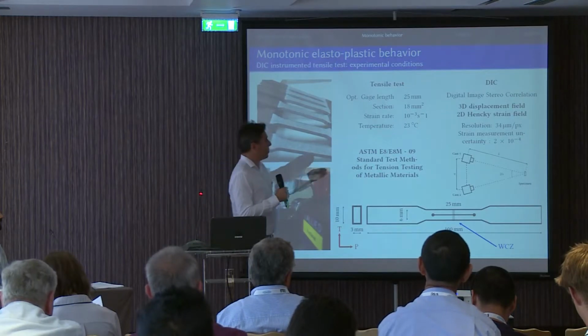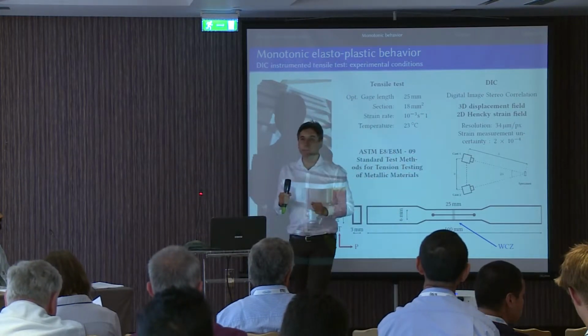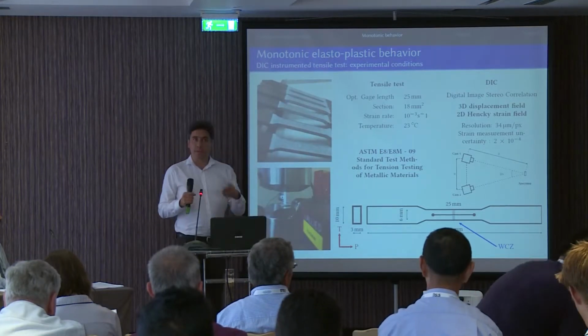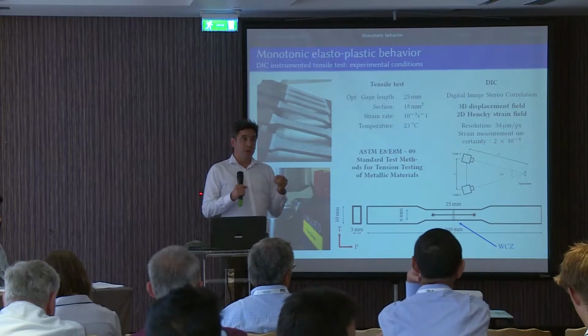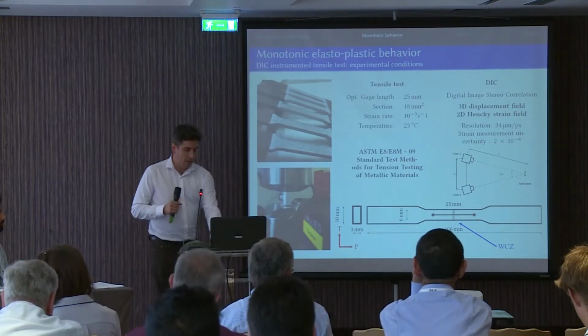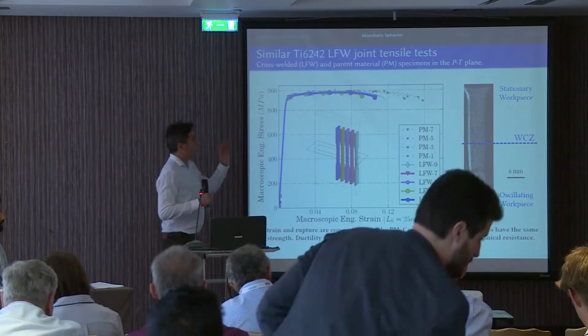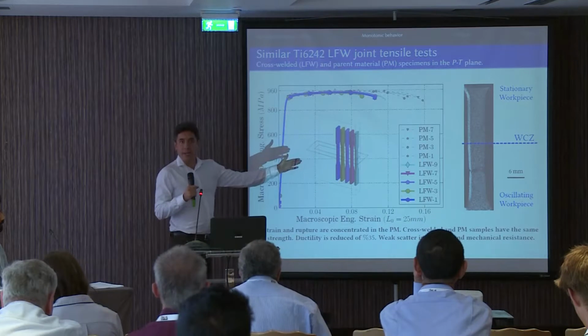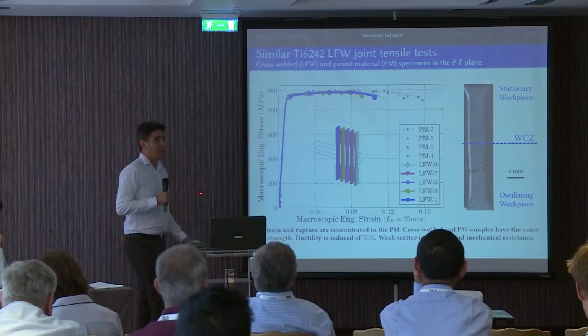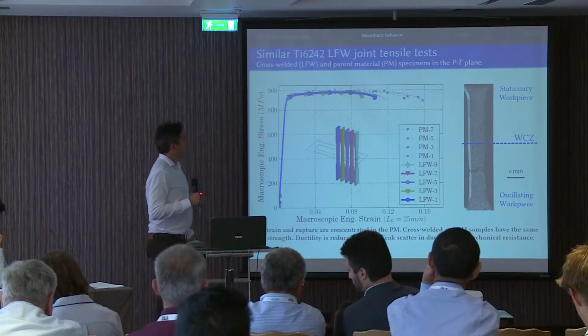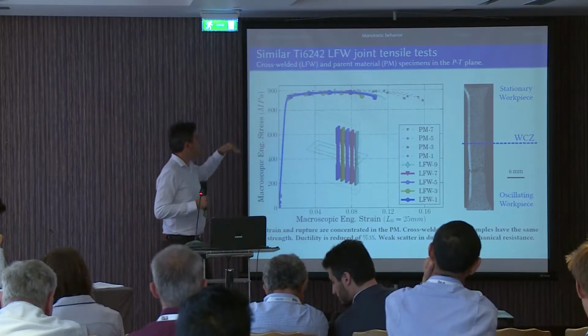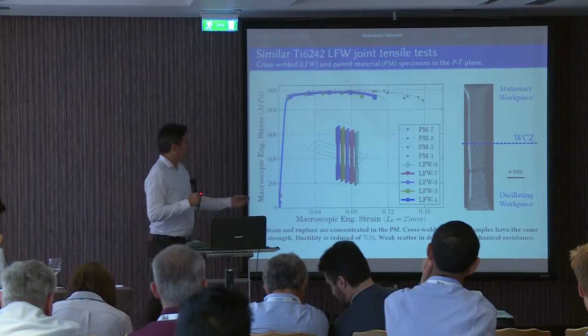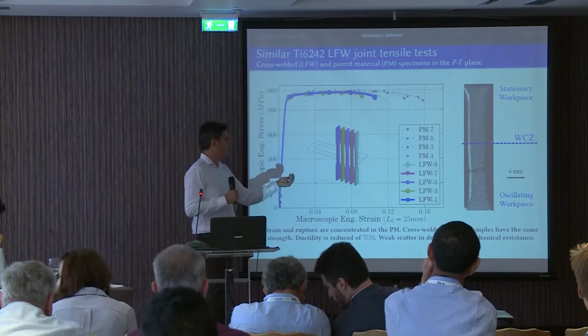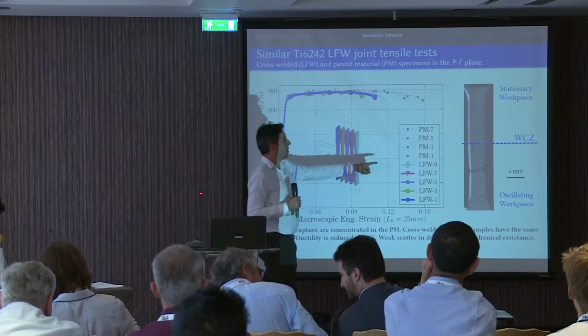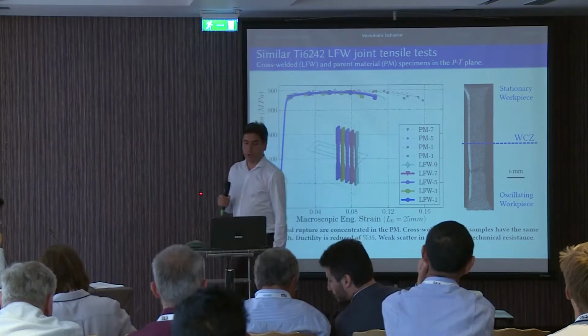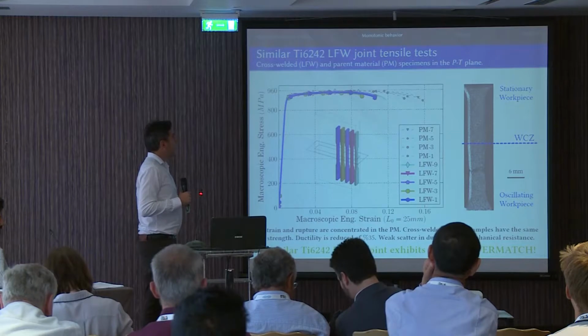But for now, I would like you to know that we are going to get the 3D displacement field and the 2D strain field on the surface of the specimen, which will allow the local behavior to be studied. First, the tensile test results. We have in colors the cross-welded specimens and in gray the parent material specimens. As you can see, the ultimate tensile strength is 960 megapascal for both sets of specimens. The ductility for the cross-welded specimens is reduced, and failure takes place far away from the weld. So we have the second conclusion of this presentation.